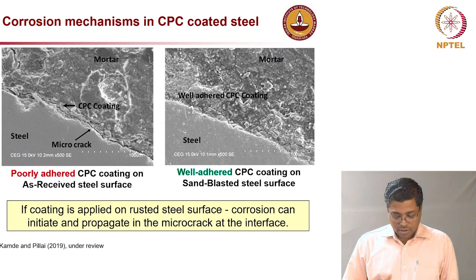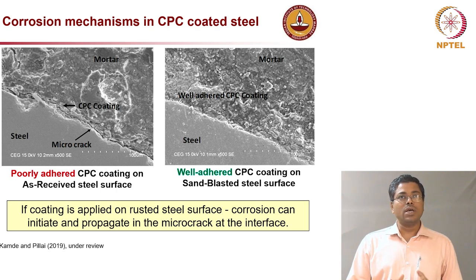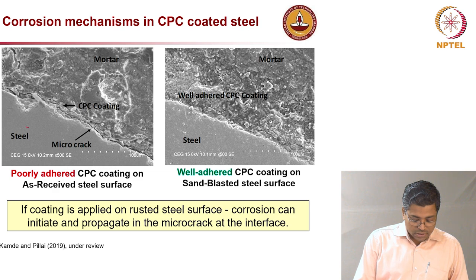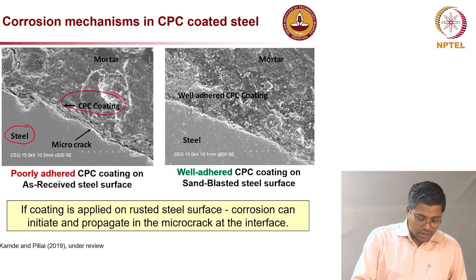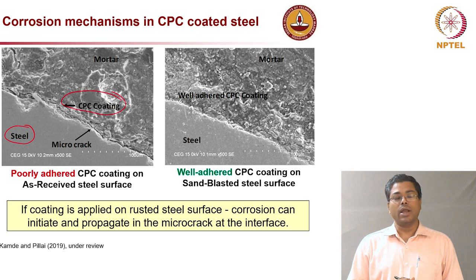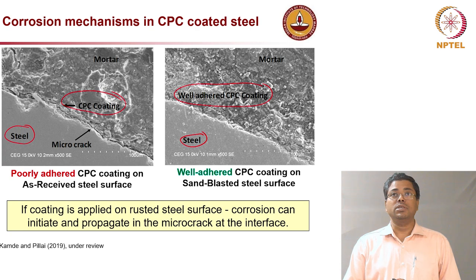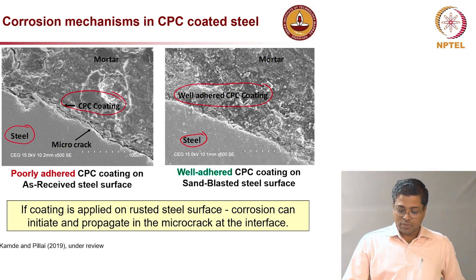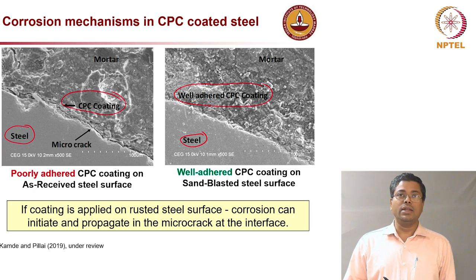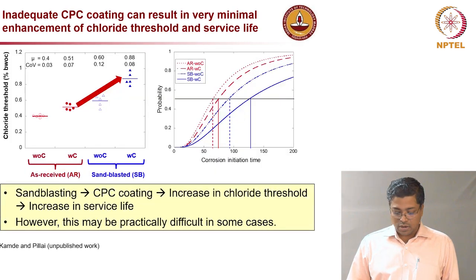Microstructural analysis: the left micrograph shows the steel with a micro-crack running all along the interface between the coating and the steel surface in the AR case. In the SB case on the right side, the steel and the well-adhered CPC coating have no crack at the interface. Surface preparation plays a significant role in determining how the service life is affected.